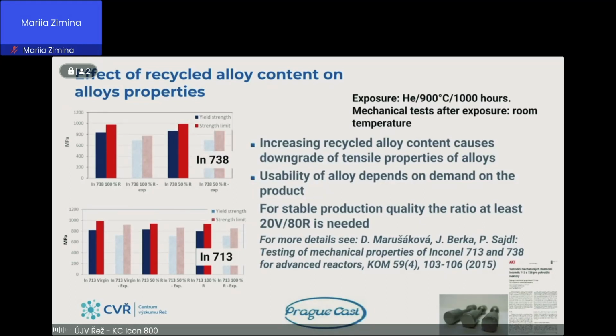So what we also tested was the effect of recycled alloy content on alloy properties. It was in cooperation with a casting company. What was the goal of this investigation? During the production of high temperature components by precise casting, a relatively huge amount of waste alloy is produced. This waste alloy is returned back to production and blended with virgin materials. And the question was if the revert material influences the quality and mechanical properties of the alloy.